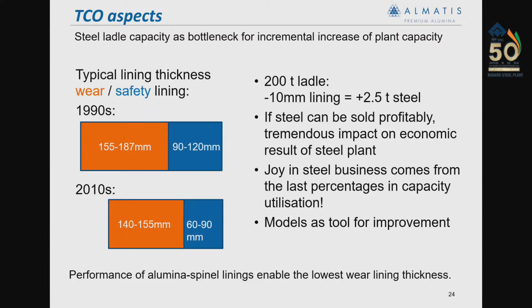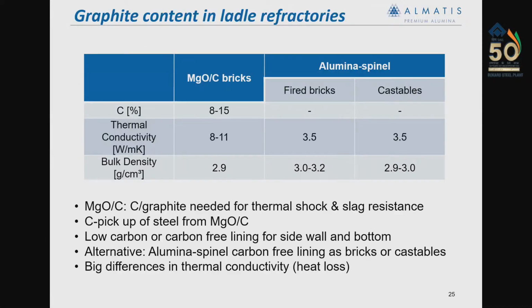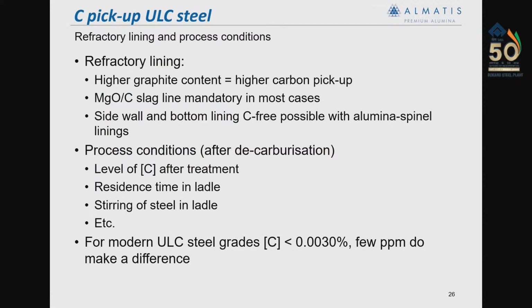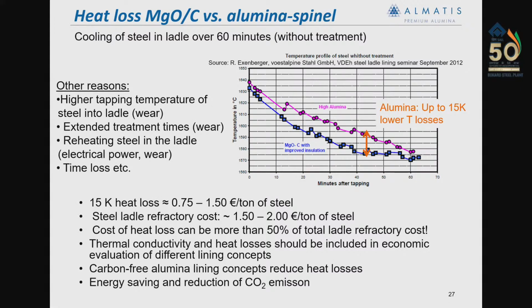And the solutions are obviously with reduced graphite content or carbon-free linings, where we can really reduce the graphite content, and at least where magnesia carbon is really essential, we can focus on that, and the rest of the things we can eliminate with synthetic alumina. If we really need to achieve ULC steel demand, where carbon is in ppm just, so 1 to 2 ppm will also make a real change. This will also save energy, not only for reheating but also for temperature reduction and processing time, CO2 emission, and metallurgical demand achievement. And this is a picture to show that with the same operating parameters, same steel plant, a lining can save just 15 degrees thermal loss. This saves 50% of your total refractory cost.